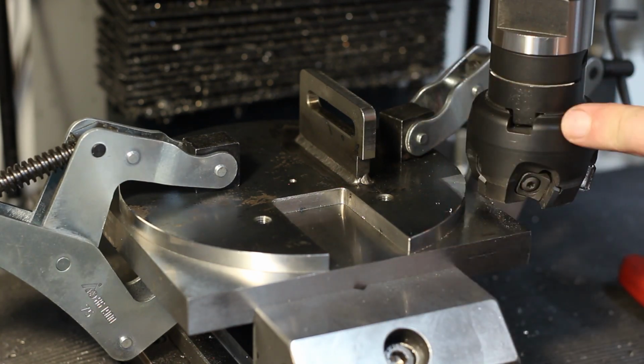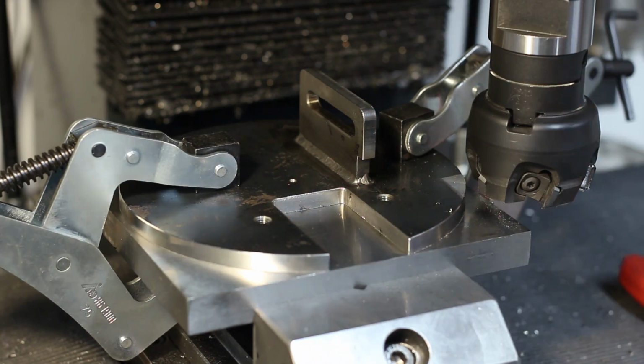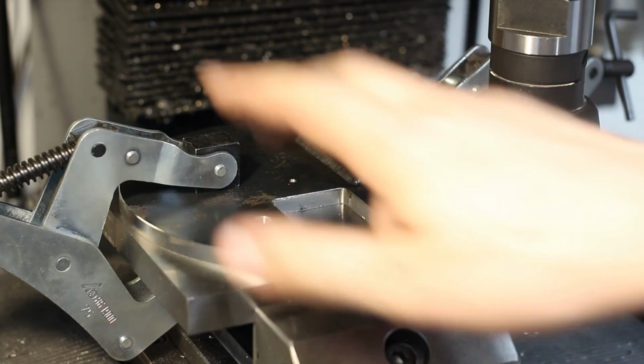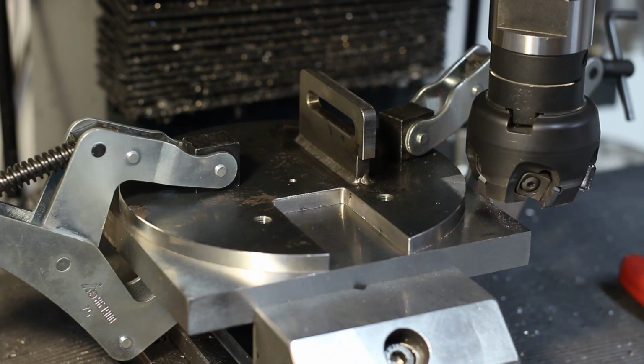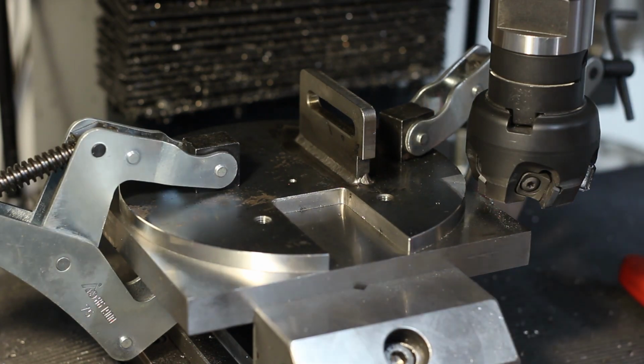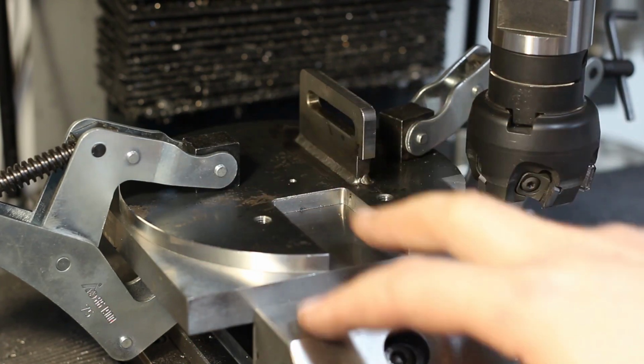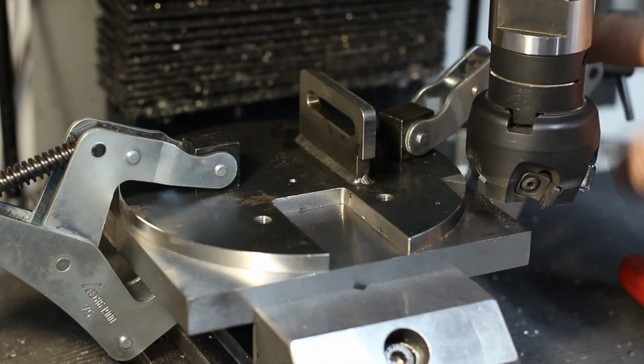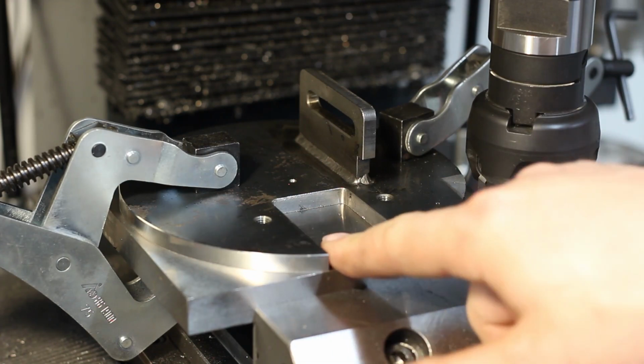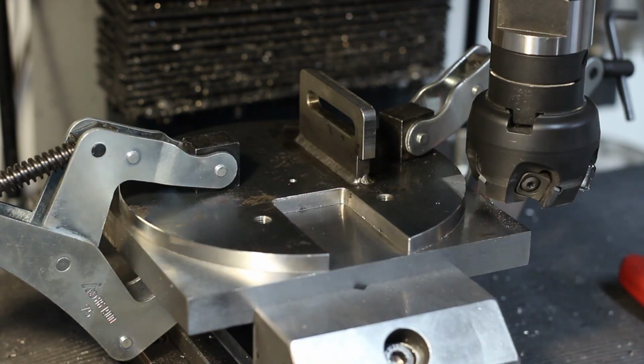60 millimeter face mill running at 1000 RPM, taking 0.2 millimeter cuts. This setup is not the most sturdy, but it's fast to set up. This is just a tooling plate, a large parallel in the vise, and 2 clamps holding the table with the machine surface down onto the plate.